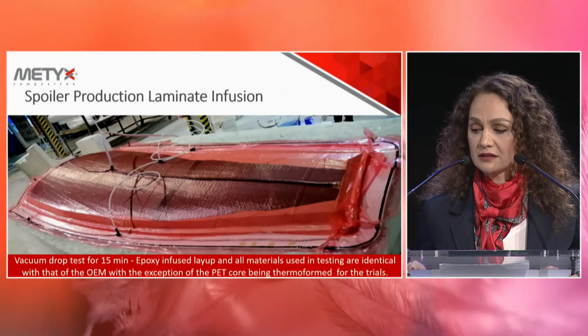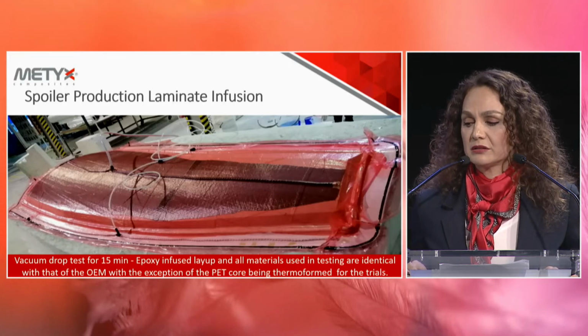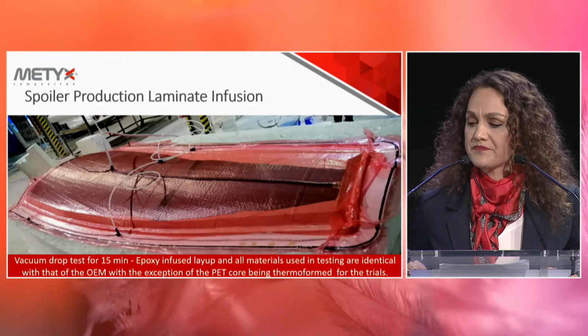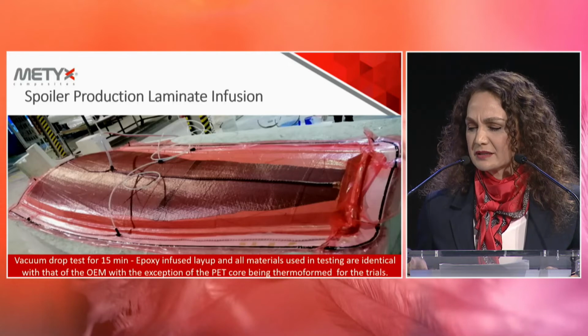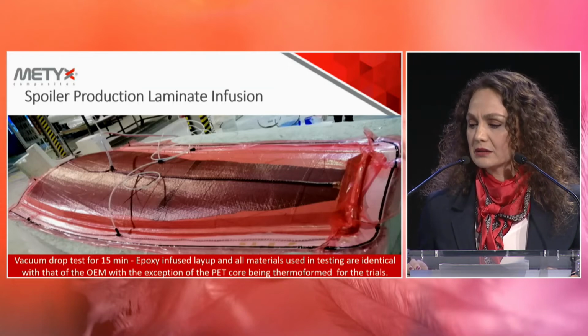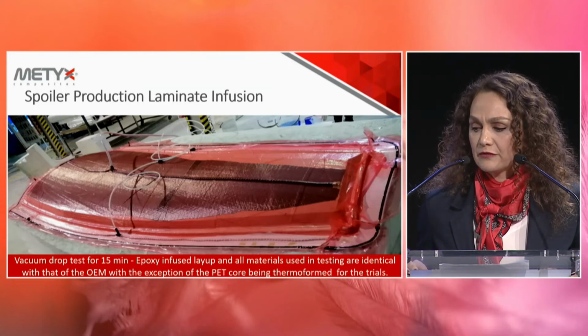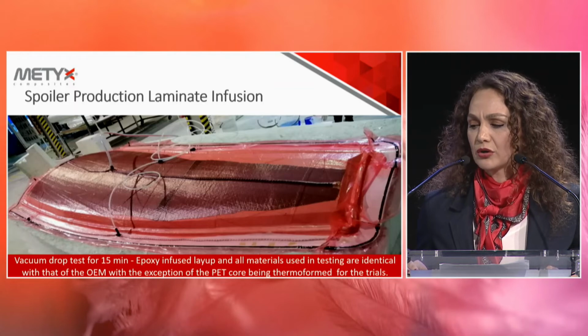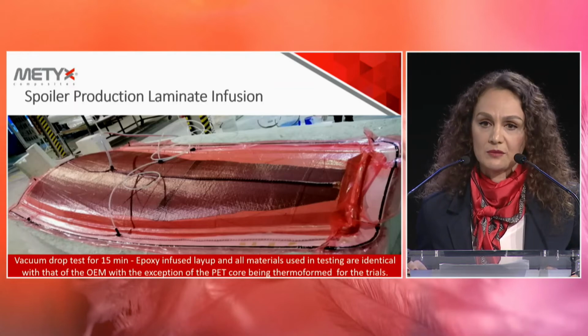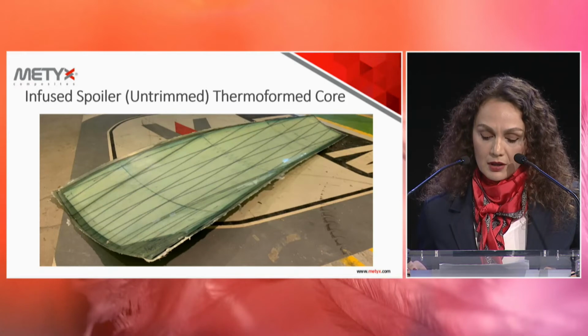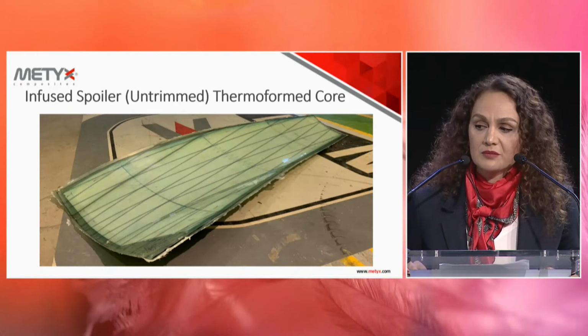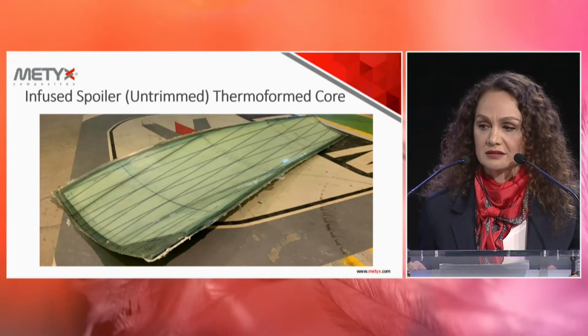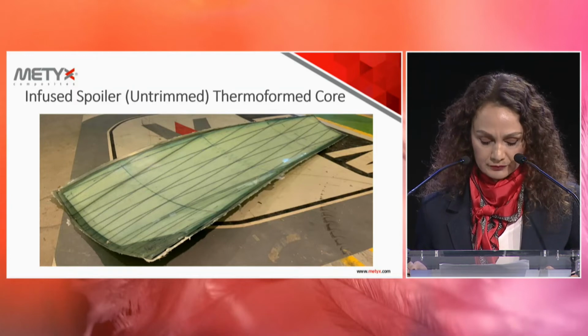So we applied the 15 minutes drop test. Everything is identical with the classical infusion, with the exception of the PET core being thermoformed with the adaptive mold here. So this is the untrimmed, demolded part produced with the thermoformed core.